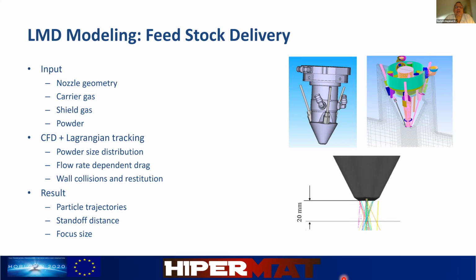We take the powder size distribution into account. So you will see that larger particles will have a larger mass and a higher inertia, so they will probably fly towards the point of intention, whereas lighter particles may be disturbed by cross-flow or switching of directions of the shield gas, so the smaller particles might be lost for the process. So the size distribution is an important factor to identify how much of the powder is really captured in the melt pool.